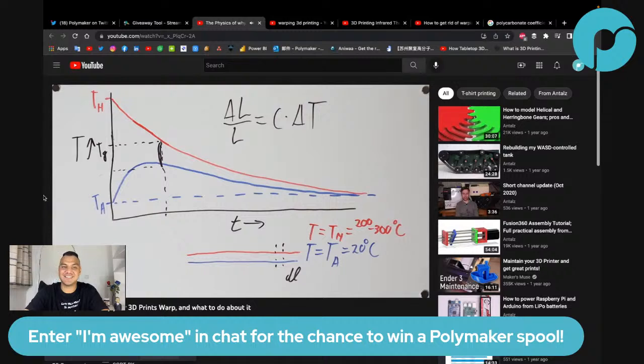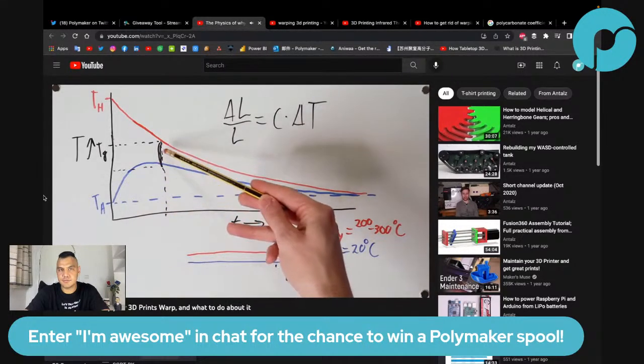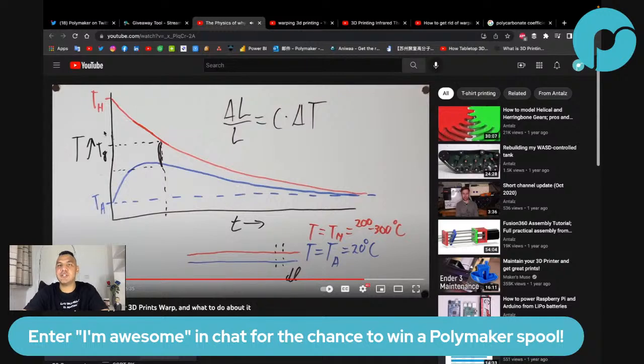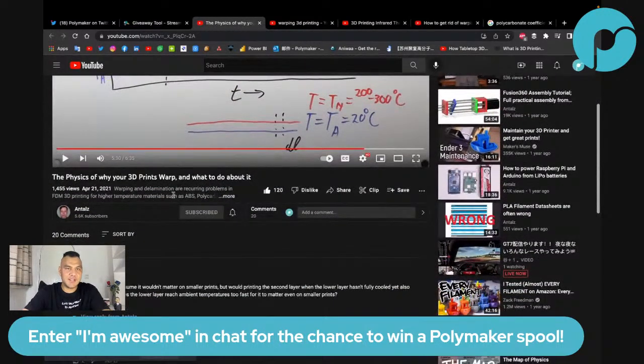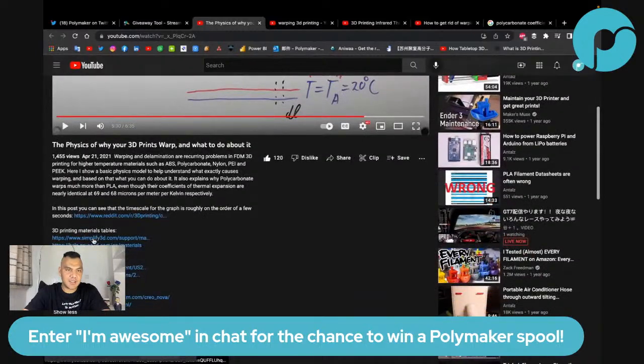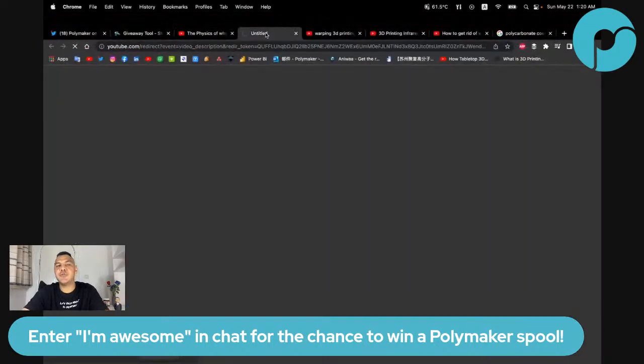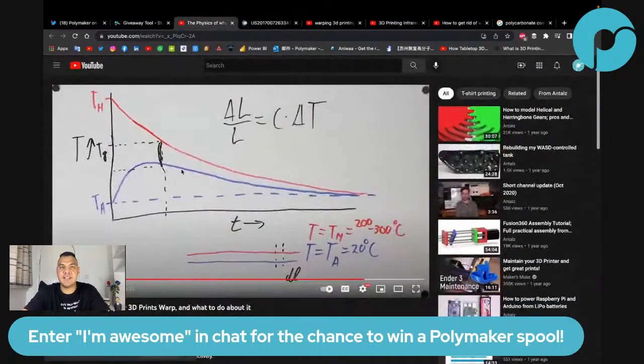In 2016, the University of Arizona received a patent where they preheat this lower layer using a laser, again to reduce the temperature difference here. Okay, so he's mentioning a patent that I think he linked, and where is that? This one. I didn't read the whole patent, but the first thing I did is look for the keyword warping, but there's no warping. So he's saying that this patent helps with warping because they heat up this layer before this layer, so that the gap is smaller, and therefore reduce warping.